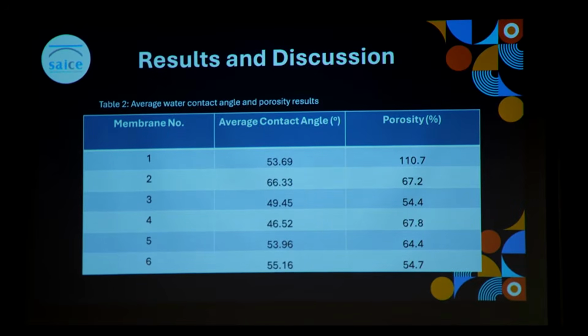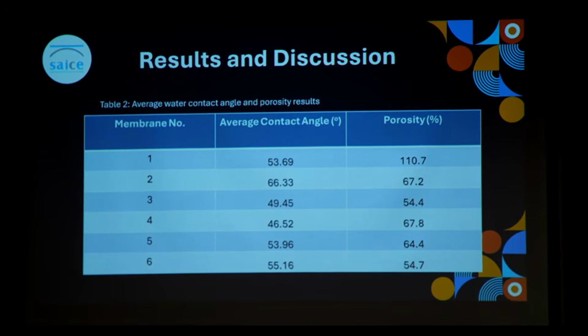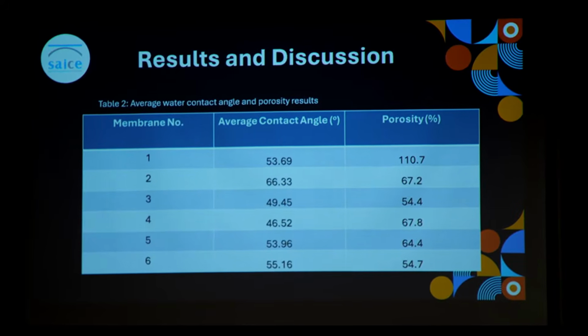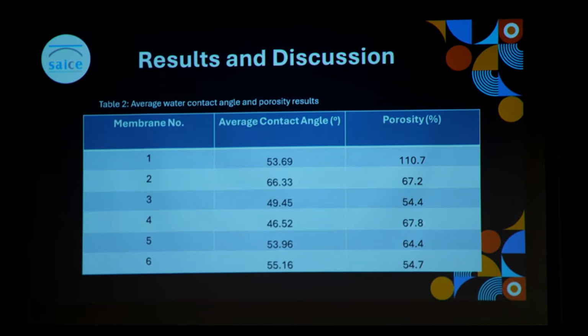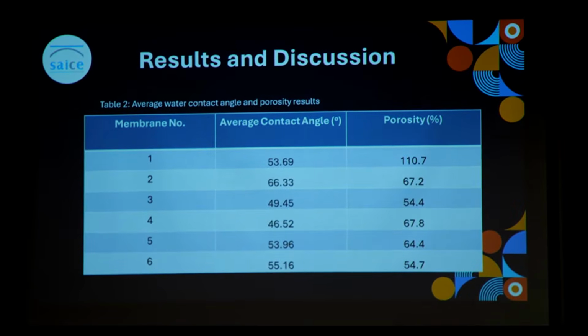Porosity measurements further confirmed the complex influence of PILs on membrane structure. While most of the membranes had a moderate porosity, membrane 1 stood out with a value above 100%, which is not physically realistic. This was likely due to membrane swelling or experimental variation. Overall, the lack of a consistent trend suggests that factors such as swelling behavior and structural distortion play significant roles in determining porosity.